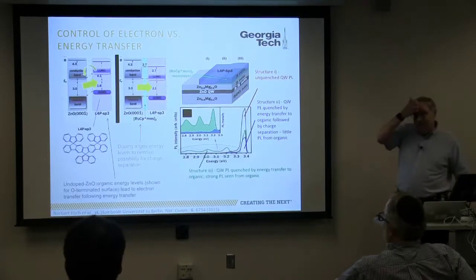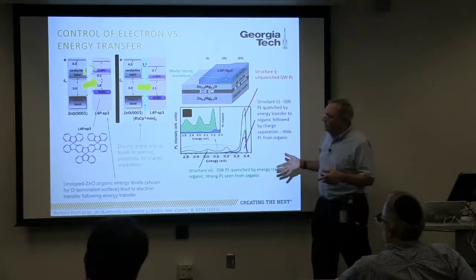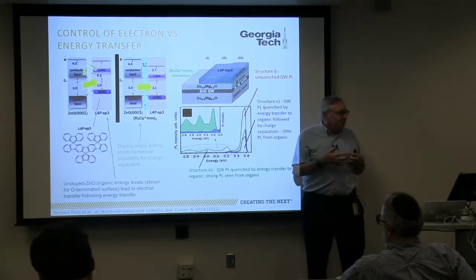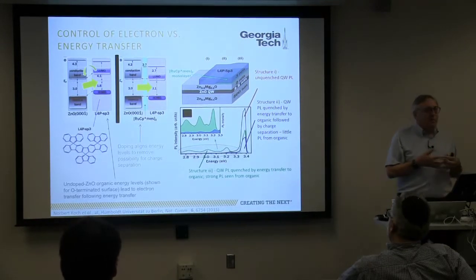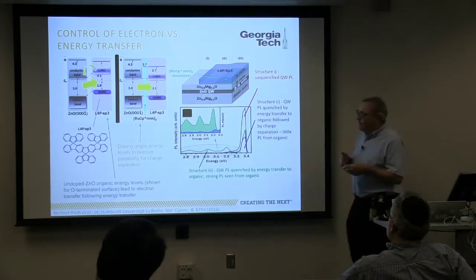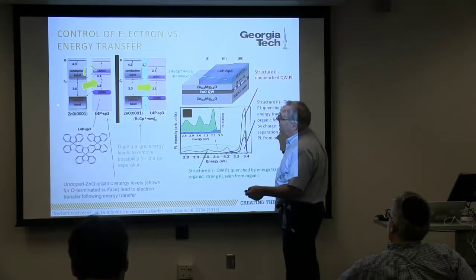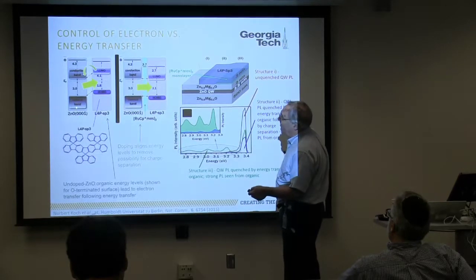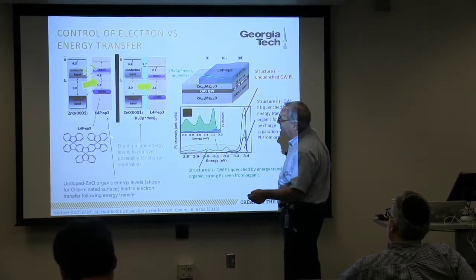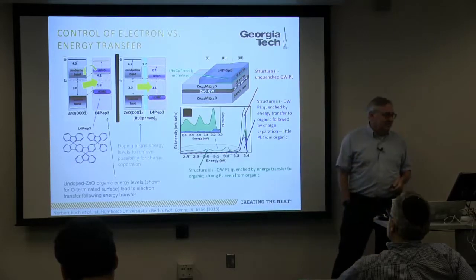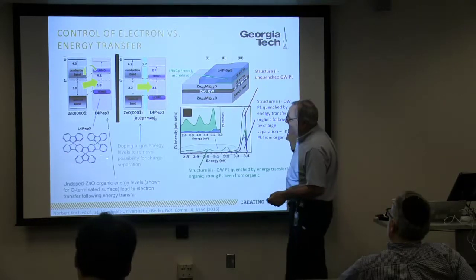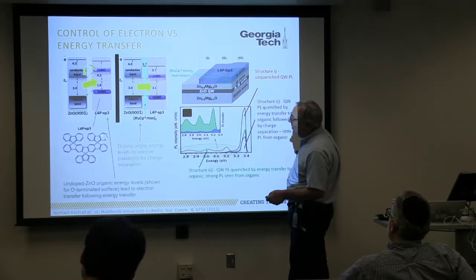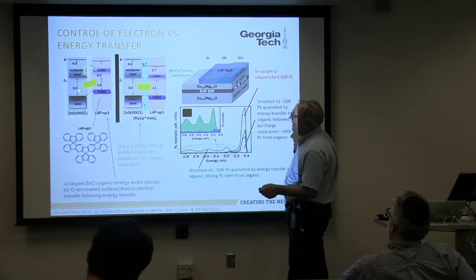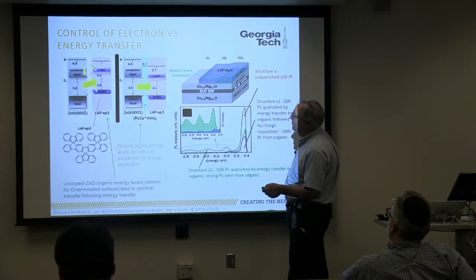Now there's another interesting thing here, and I won't go into all the details. But what these folks were interested in doing was making a hybrid light-emitting device where they created an exciton in the zinc oxide. And then we're going to transfer that exciton to this material, which is highly, highly emissive. And they designed this material such that its HOMO-LUMO gap was just slightly smaller than the band gap of the zinc oxide. However, instead of getting a type 1 interface, they got a type 2 interface.